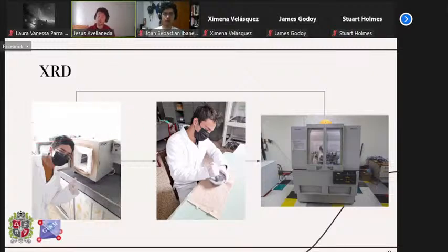So if we want to be sure of a complete and successful sintering process, and if we also want to evaluate other responses of the material, this pattern was essential. As my friend said, after each sintering process, we also ground the sample for roughly half an hour, and the resulting powder was sent to the XRD lab. This cycle was repeated for all the sintering curves.